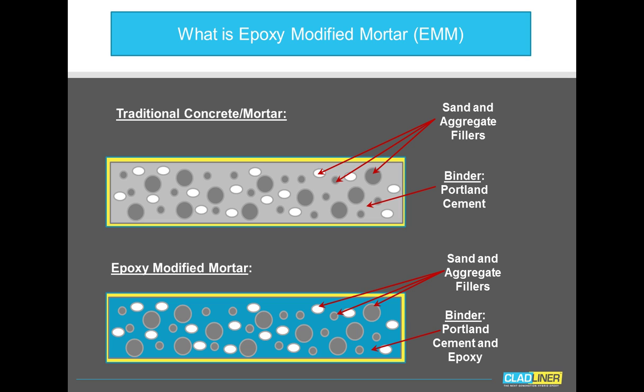Typically what we find is very similar, if not the same, types of aggregates and fillers, because these are what ultimately create the structural strength or the compressive strength of the product. However, in this case, the binder is a Portland cement and epoxy blend. We have a waterborne epoxy that is fused with the Portland cement to create the binder, which creates a totally different matrix for the epoxy-modified mortar product than a traditional cement does.